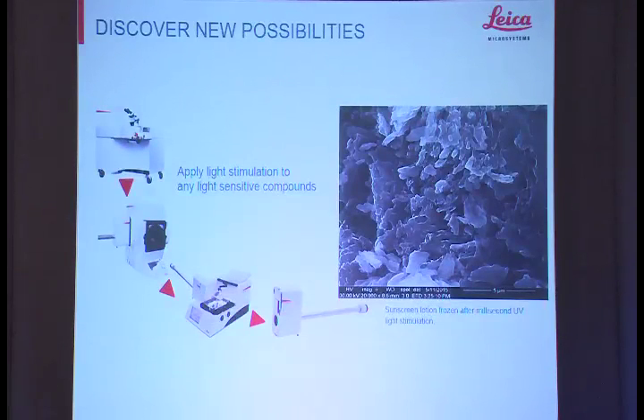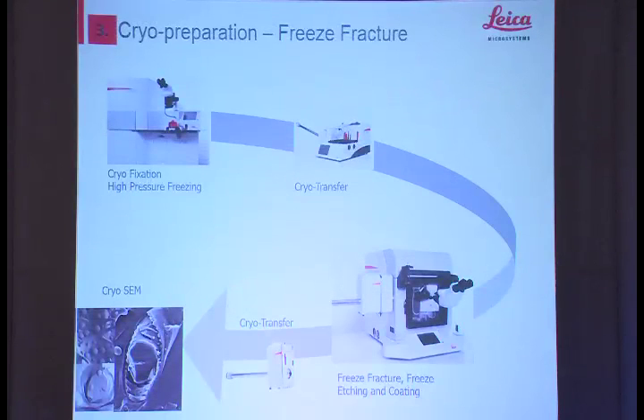The sample itself can then be used for a variety of follow-on techniques, from simple processing, sectioning into the electron microscope, or in this case, this is sunscreen lotion that was frozen in the high-pressure freezer and then freeze-fractured. This was UV stimulated, so UV light, of course, is going to have an effect on sunblock to stop pale people like me from going red. And this can then be seen as changes in the electron microscope. So we can use these pathways to help us.